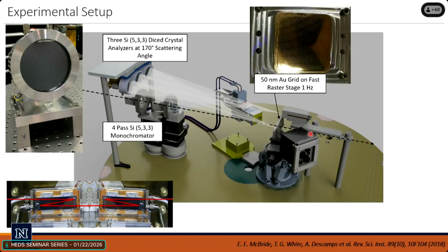Then we have our spectrometer. And with the spectrometer, we still need to measure this extremely high resolution, right? We don't want to ruin it. And so the X-ray spectrometer is a very special spectrometer. Normally, you would take a crystal, you would bend it into the shape that you want, and that would be your spectrometer. But if you bend a crystal, you introduce strain in the lattice, and that can reduce the resolution of your spectrometer too much, and you won't be able to see the small shifts we're looking for. So we use these diced crystal analyzers, which is just a way of saying that it's made up of hundreds or thousands of flat single crystals that are positioned in the right location. They're extremely expensive, but they don't reduce the resolution of the spectrometer.